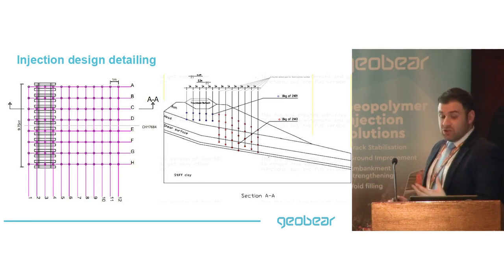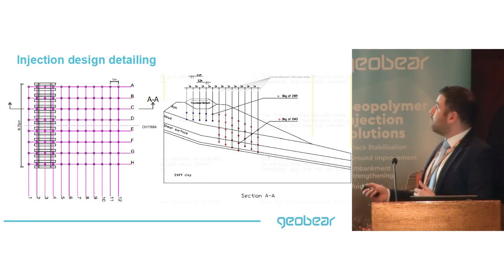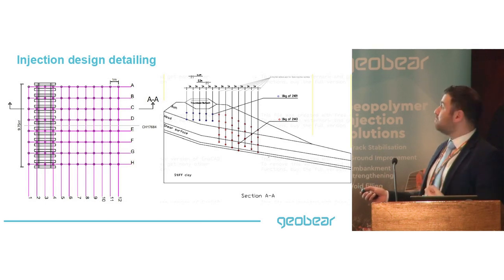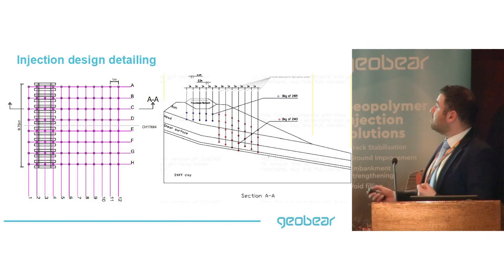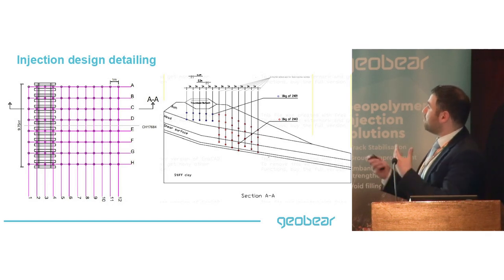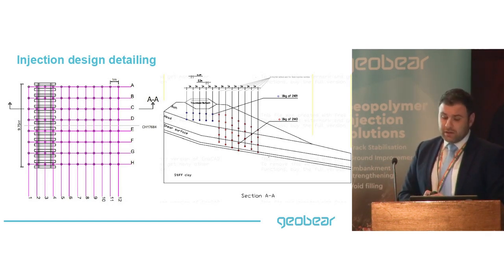We carried out the injections at different levels. Under the track we treated the ash, and as we stepped away we increased the injection intensity, using a high density geopolymer to treat the shear surface and inject through it, with different materials and injection dosages.